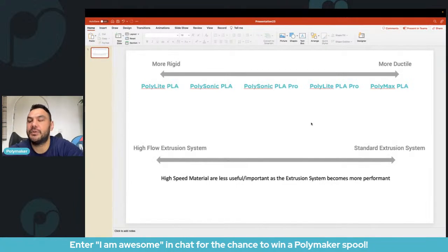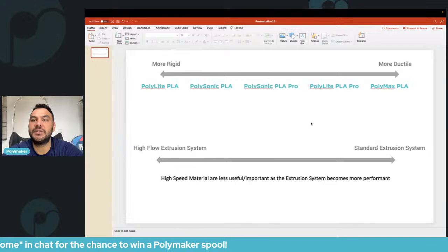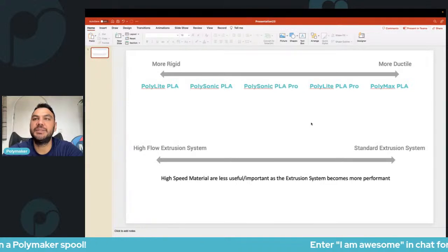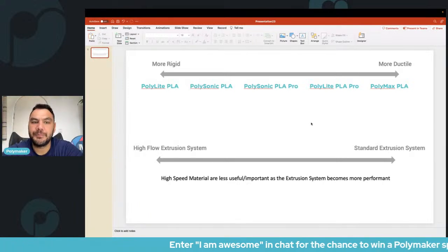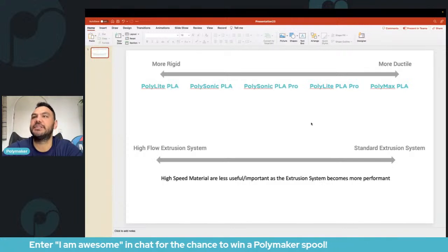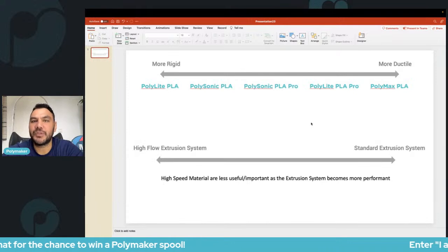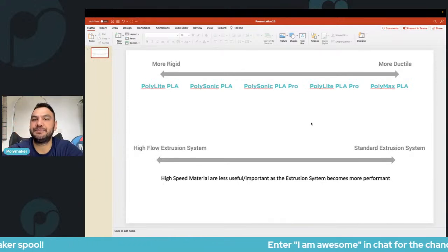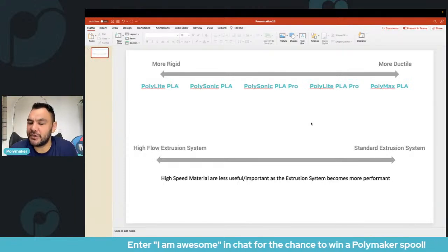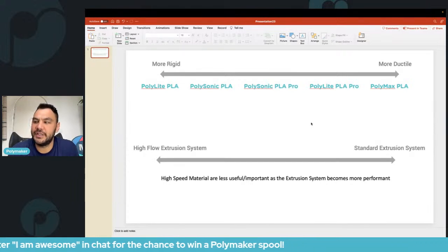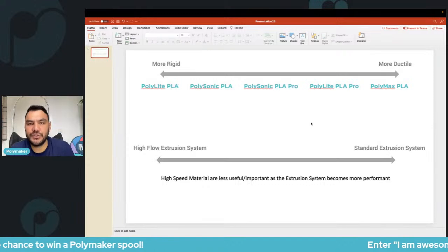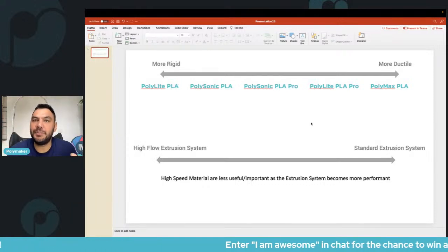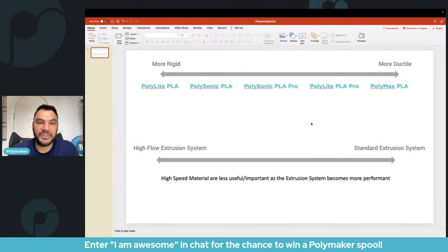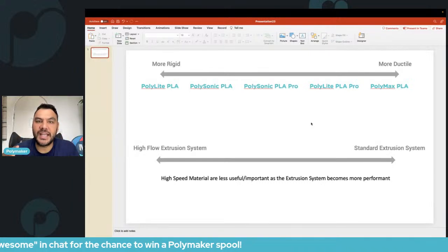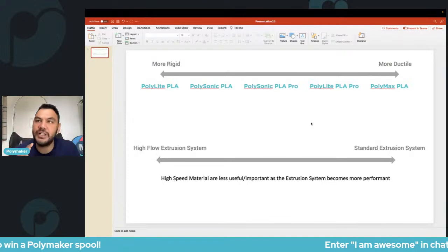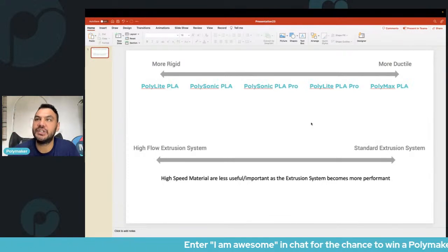question is important. For example, we did a test where I sent some Polysonic to speed benchy participants, people that are on the leaderboard of the speed benchy, and they tried the Polysonic PLA and they didn't find much difference. They said their regular PLA does as well, if not better. I was so surprised. I was like, oh my God, we developed the Polysonic PLA to be much better. But then we understood that it came from the extrusion system. These people on the leaderboard for the speed benchy have such a high flow extrusion system that the material doesn't need to be high speed because the hardware already allows them to print those materials.